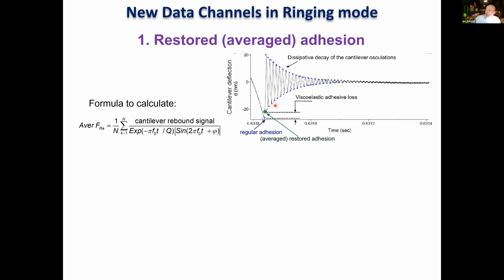But we can compare this energy loss to the size of the neck, because we know how much the neck is pulled, we know the adhesion, and we have the pull energy of the neck. So we can see that this is a loss due to molecules, or at least something, because we see a mechanical signature. It is something much weaker than the interaction with the neck. Of course, it is our assumption that this is a bunch of molecules, because what else can it be?